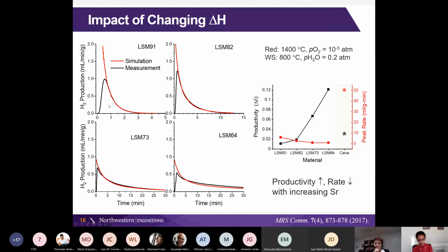And the simulation and the data here are in relatively good agreement again, telling us that, in fact, this is basically what we expect for a material that has a much lower enthalpy of reduction. On the other hand, the productivity, so if we were able to go to an equilibrium cycle, go all the way from one equilibrium state to the next, as we have more and more strontium, we would expect more and more hydrogen to be produced, because this is a larger and larger change in non-stoichiometry. But that peak rate of production is declining.